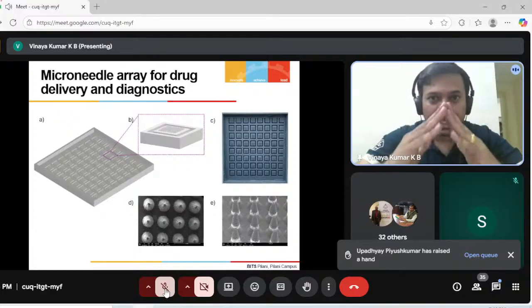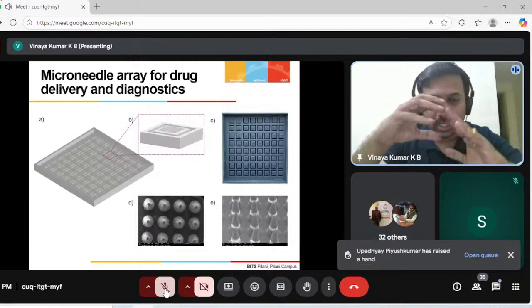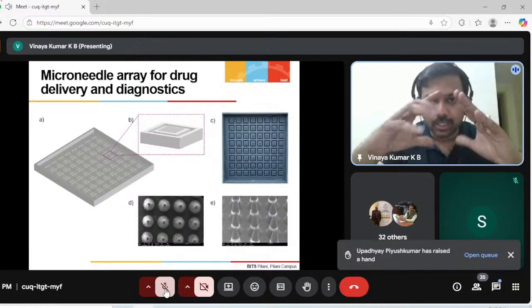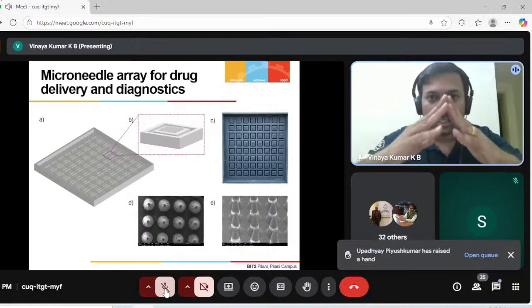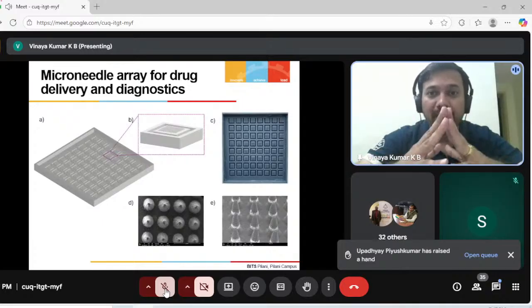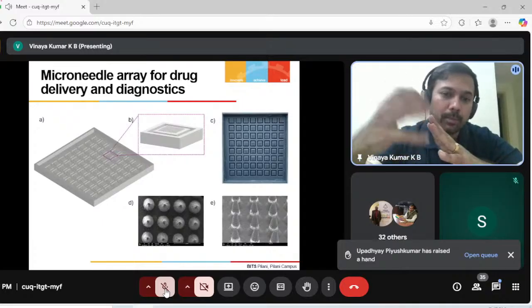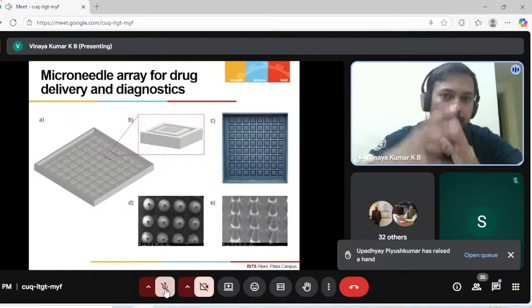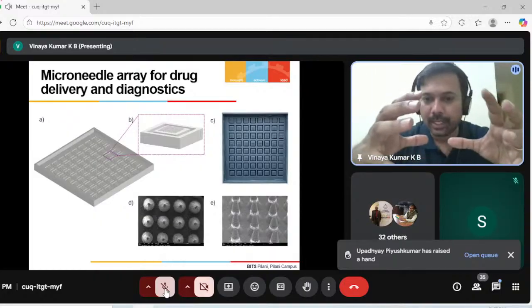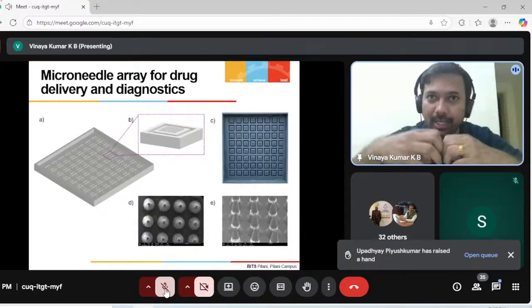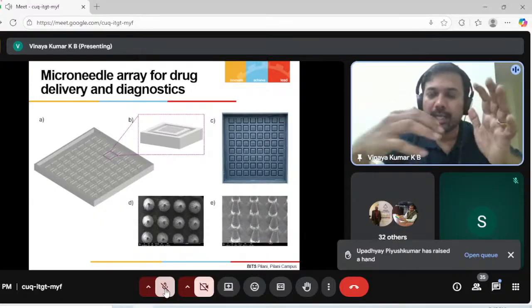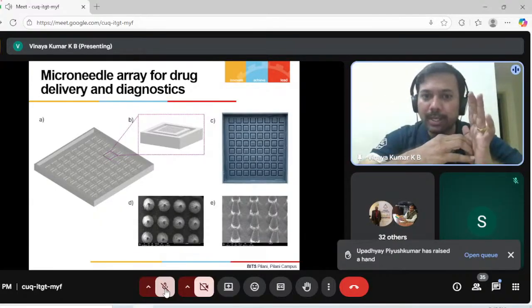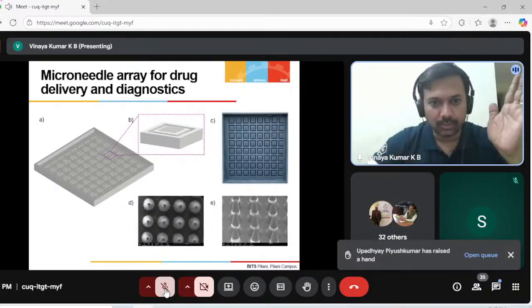The micro needles are as sharp as 30 microns at the tip, and as long as 900 microns. We were able to fabricate a 25 to 30 micron tip micro needle using a 3D printer, and then we made a mold out of it. Then we used completely dissolvable polymers like PVA and incorporated the bacteriophages in our micro needle, and then we were able to deliver the bacteriophages into the chronic wounds. So that's one of the works.